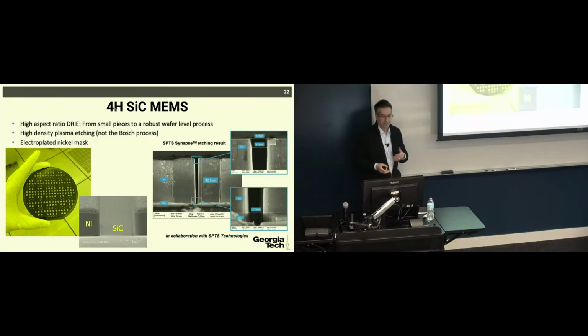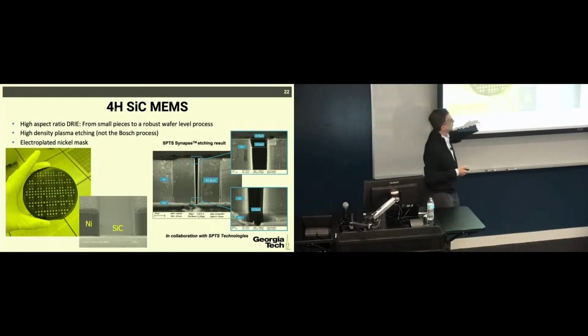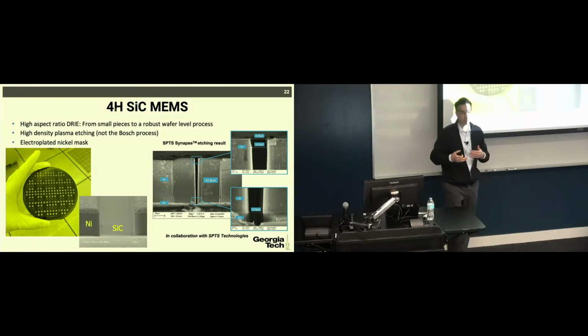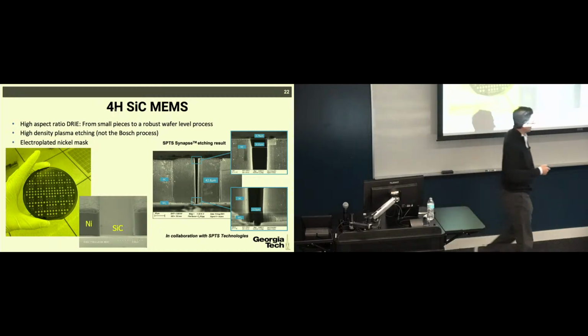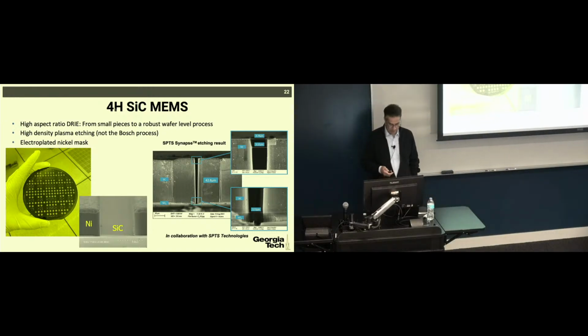And after years of R&D, we have been able to now create silicon carbide on insulator wafers. So you see that you can actually bond the silicon carbide wafer 40 micron thick. You can etch very nice looking trenches into silicon carbide. It is not the Bosch process because it has carbon inside. Silicon carbide has carbon, so it is a self-passivating process. So you just need a high density SF6 plasma etching, but you do need an electroplated mask to be able to etch deep down into the structure.